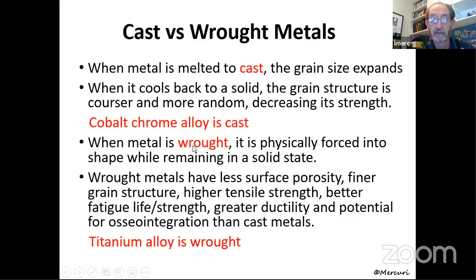Titanium is a wrought alloy. What wrought means is that these materials are not melted until we get to 3D printing, and we'll discuss that. But the typical form of titanium that's used in most devices that are not 3D printed, these materials are pushed together. So they have finer grain structure, higher tensile strength, better fatigue life, and greater ductility, and a greater potential for osseointegration. That's why we use titanium to make dental implants and not chrome cobalt. There's a 40% greater osseointegration with titanium than there is with chrome cobalt.